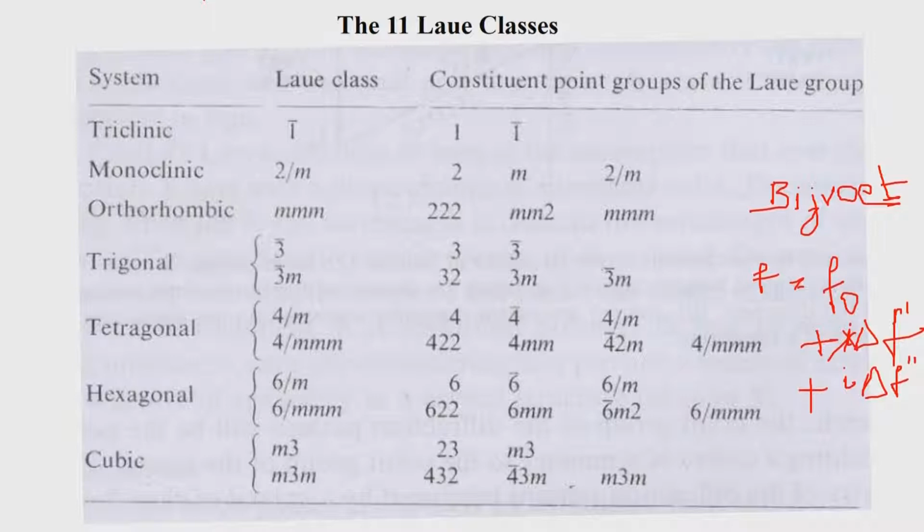The diffraction apart from that also obeys Friedel's law in most cases, and because it obeys Friedel's law, the number of point group symmetries will reduce, because we will get only the centrosymmetric information in an X-ray diffraction pattern. So, we will therefore get the 11 Laue classes. The 11 Laue classes are shown here, and the scattering is essentially this.